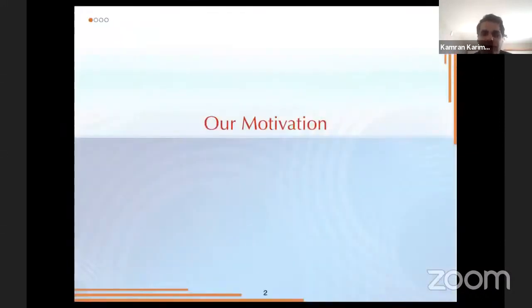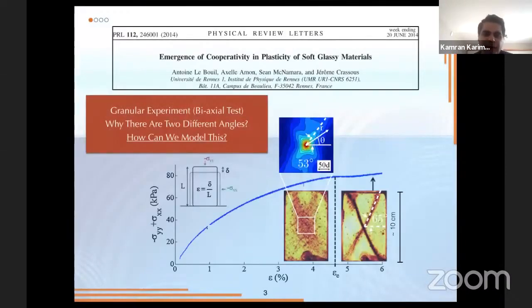Let me give you our motivation, which is a granular experiment done in Rennes at Jérôme Crassous's lab. A typical biaxial test, and they had a novel method of measuring microscopic strain within the granular sample based on the scattered light. The dark regions represent active regions. And you can see that these precursors occur before the failure, and at larger strains, the deformation localizes into these two clear shear bands.